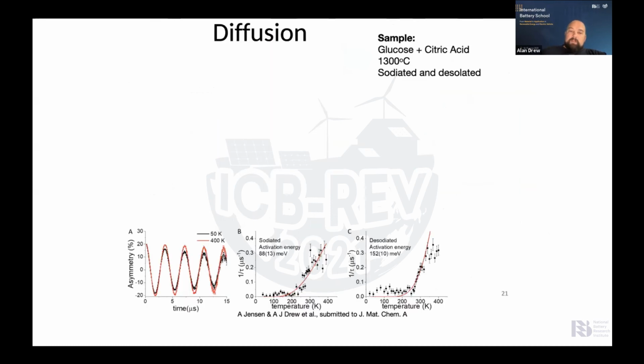We did some MUSR. Now, what MUSR does, I'm not going to go into the detail, is if you reduce, you can see here between 50 Kelvin and 400 Kelvin, there is a significant change in this signal. The amplitude of this signal gives you the diffusion rate. Or rather, actually, the relaxation. They start off the same, and as time goes on, this relaxes. So this relaxation rate gives you the diffusion rate. Essentially, the faster the ions diffuse in the material, the lower the coupling that it has on the probe, which means the lower the relaxation rate. So the bigger the amplitude at higher times.